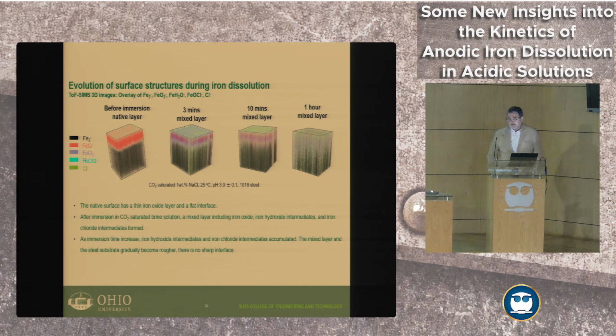Yes, that's a very good question. It almost sounds like you've worked in this area. That is the biggest challenge. What if, like you said, you have 2 pathways that involve, say, 2 different species, which happen at more or less the same rate? In other words, they will show up in these diagrams with the same loop, and there will actually be 2 of them on top of each other, but we can measure only the sum of the 2. So that is a problem, and there is no simple way to distinguish that.